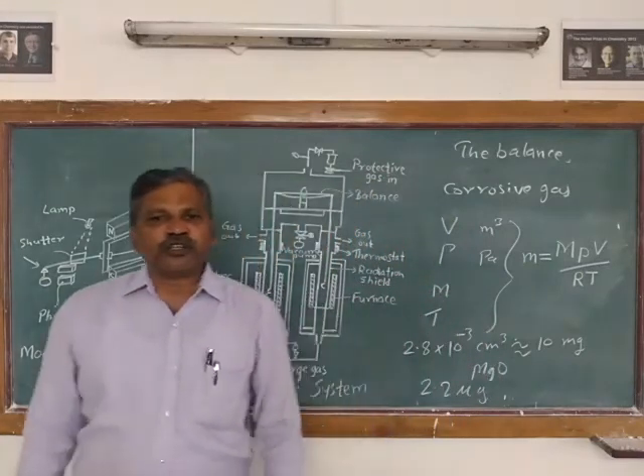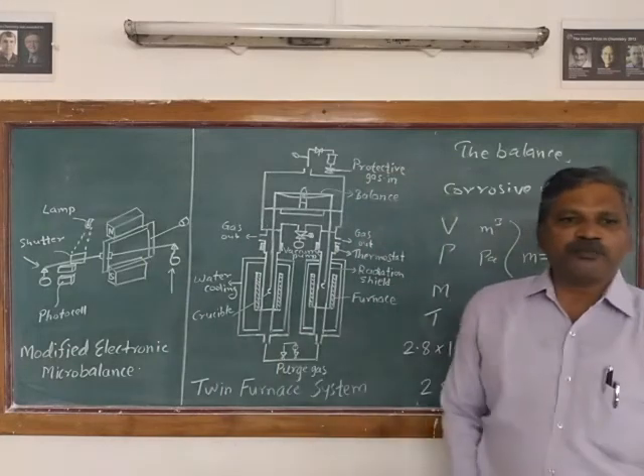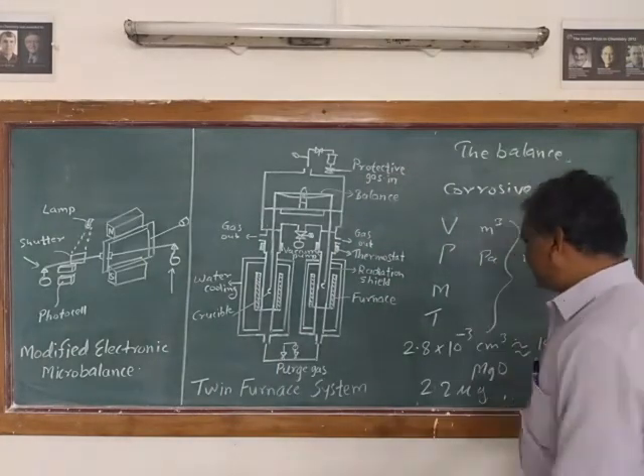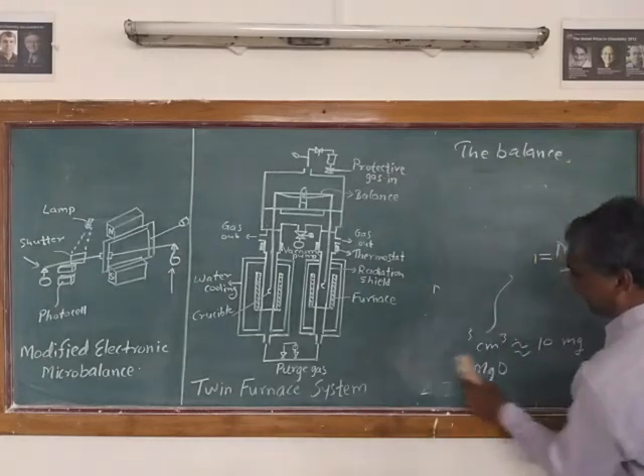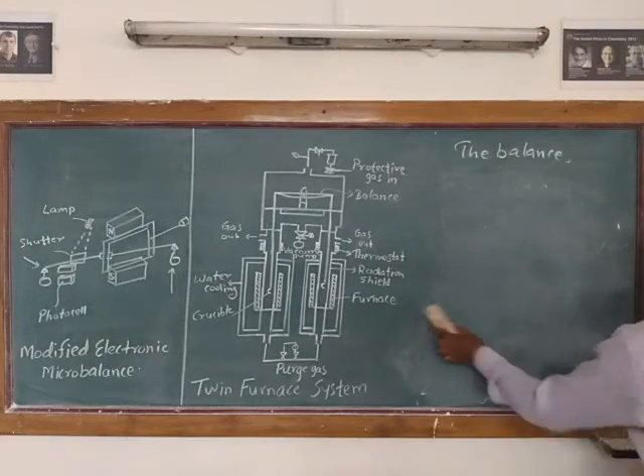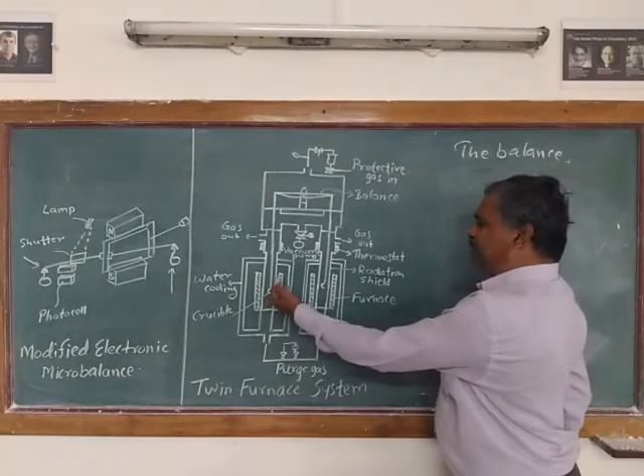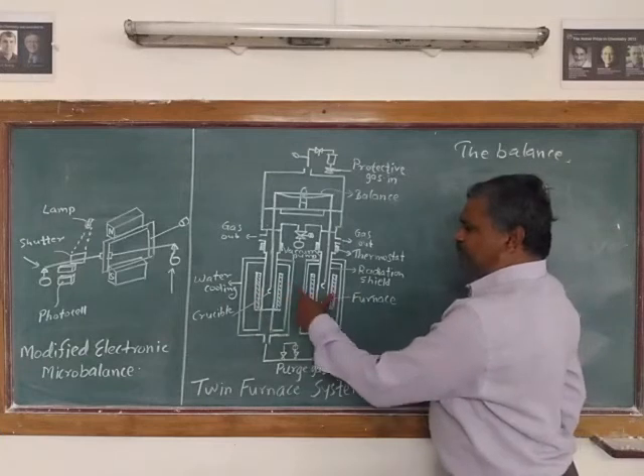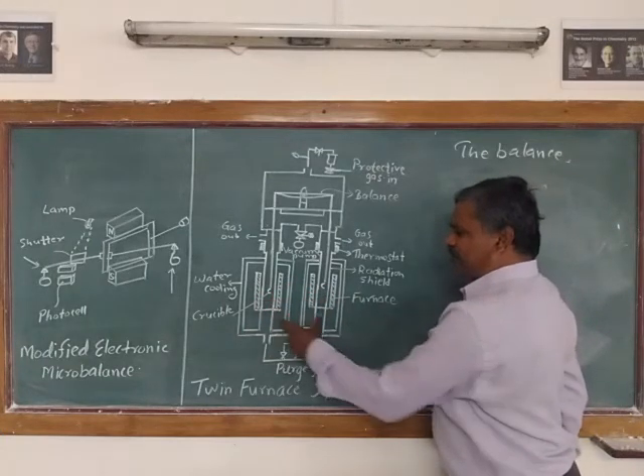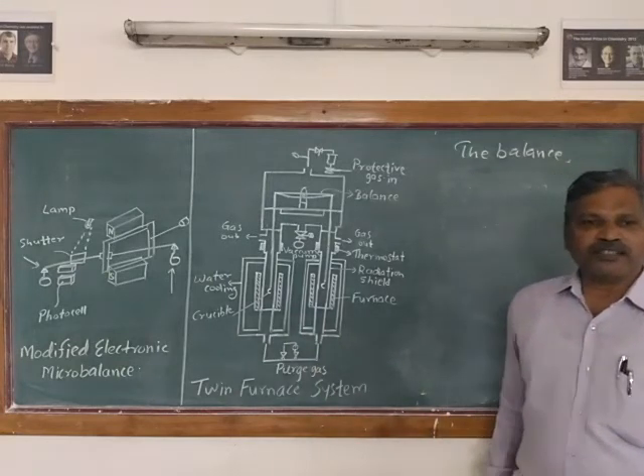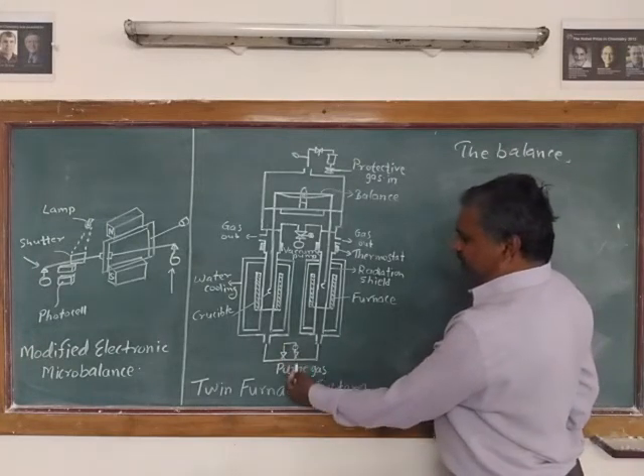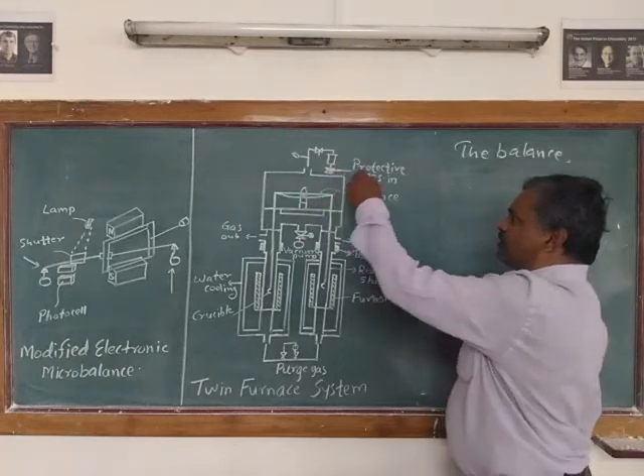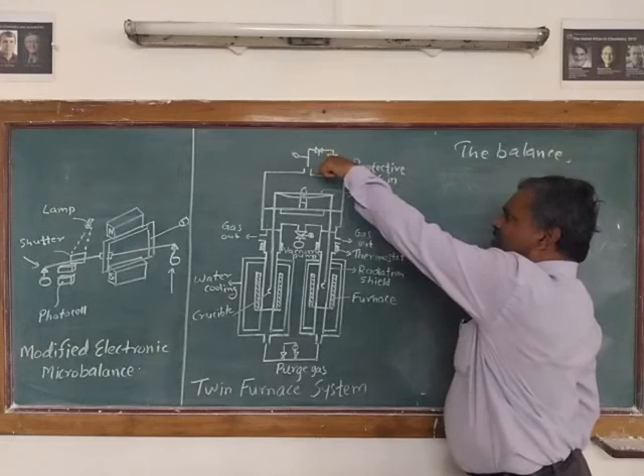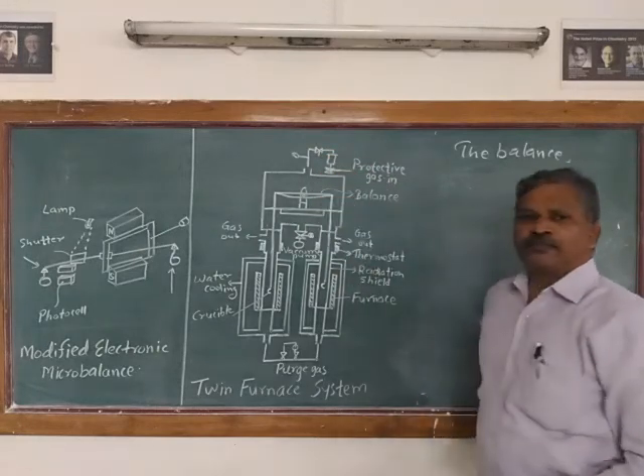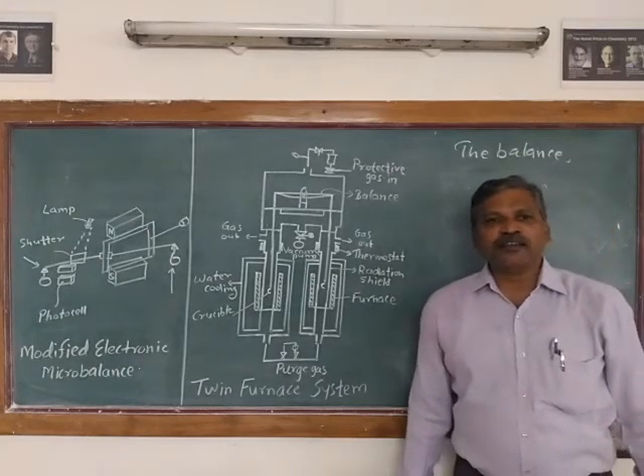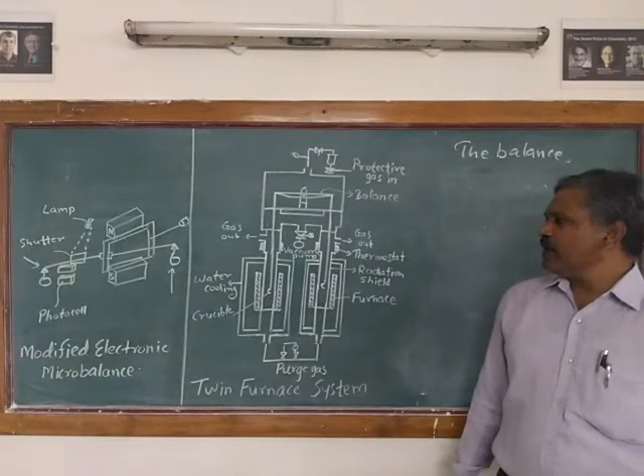Thirdly, if we use a twin furnace system where the counterpoise of a similar volume is heated at the same time, the effect is largely cancelled. Here we have shown the diagram of the twin furnace system. On one pan the sample is there, on the other pan the reference material is there, and both are simultaneously heated by using the two furnaces. So it is called a twin furnace system. Here we purge the inert gases so that the corrosive or oxidizing gases evolved are carried away. From here we can insert the protective gas so that it will protect our thermobalance. So by using this twin furnace system, we can avoid the gain in the mass of the sample.